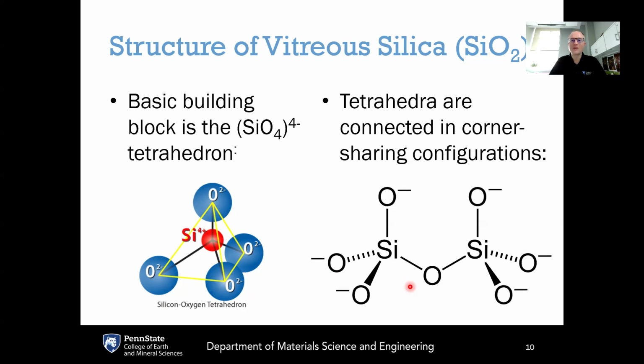The question now is, does silica follow Zachariasen's rules? This is the basic building block of silica glass, the silicon tetrahedron. What we can see here is that this silicon cation in the center of the tetrahedron is surrounded by 4 oxygens. So this satisfies Zachariasen's second rule, that the coordination of the oxygen around the cation is either 3 or 4. In this case, it's 4. Each oxygen here is coordinated with 2 of the cations, so it's coordinated with 2 of the silicons. So this satisfies Zachariasen's first rule.